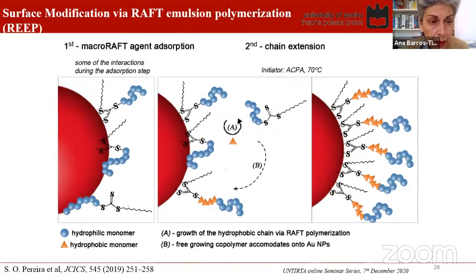Now, in terms of what happens to this macro RAFT agent during the first stage, which is the adsorption, we believe that there are interactions during this adsorption step that involved the coordination between the sulfur groups onto the gold surface, as well as interactions of the PEG chain with the gold surface. When chain extension takes place, so when these macro RAFT particles anchored to the gold nanoparticles are dispersed in water, so that we proceed with the chain extension,